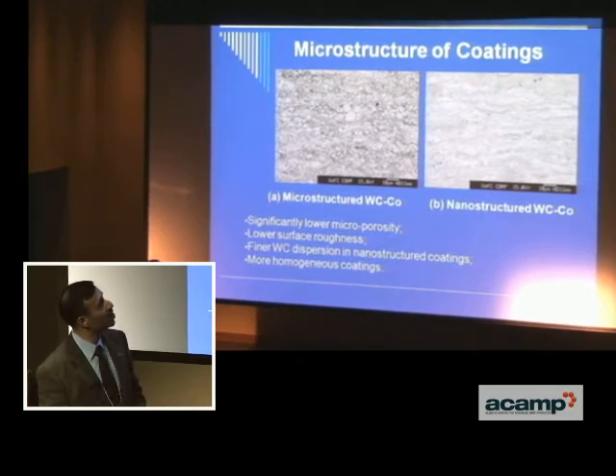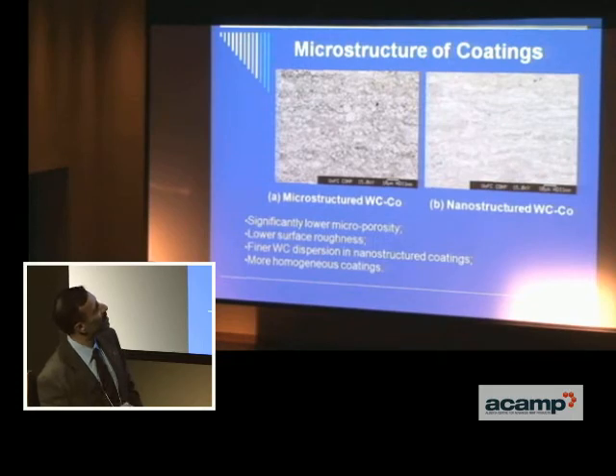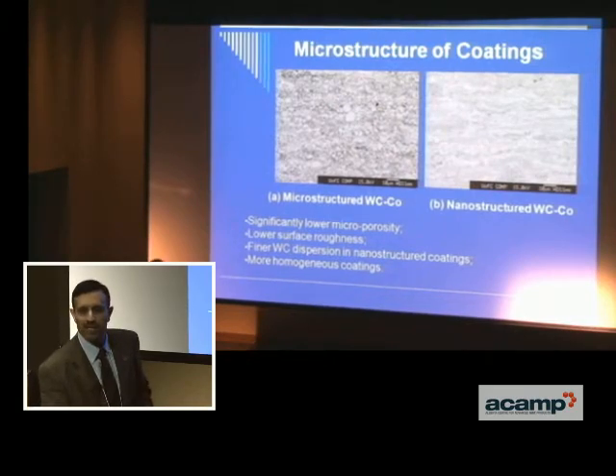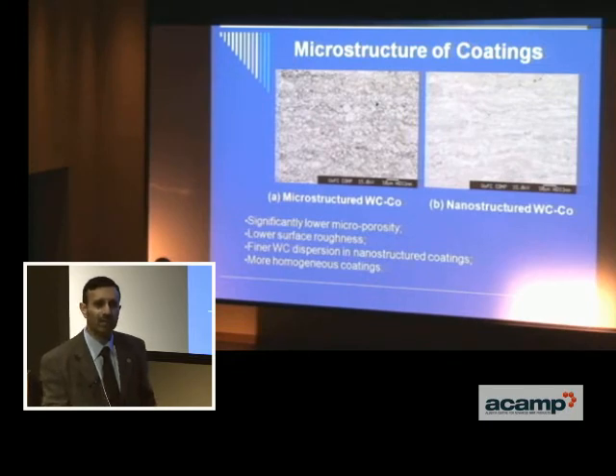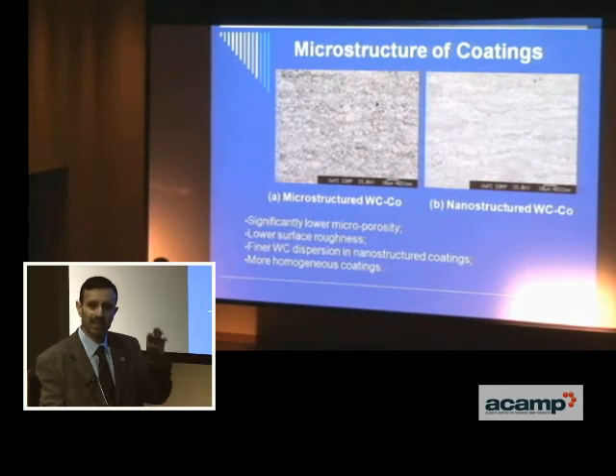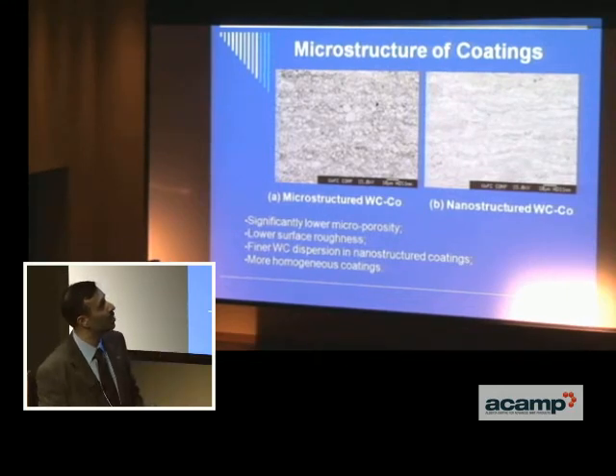What we find with the microstructure is that you can see the tungsten carbide, WC powder, distributed randomly throughout the coating itself, but here you can't see the carbide dispersion whatsoever. One of the reasons is that we've got a much finer dispersion spread throughout the coating, and that does different things to the chemistry of the powder as well. We're also using a cobalt matrix, but we're also protecting the powder with a cobalt layer outside as well. That does different things to the powder. It helps flow, but it also helps cement or bind the WC dispersion within the coating.